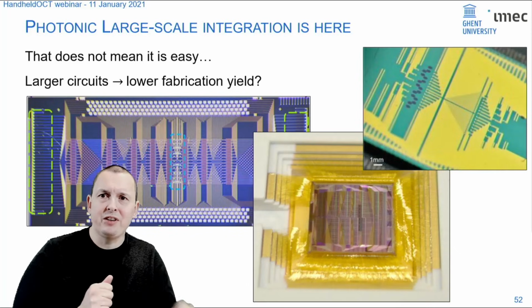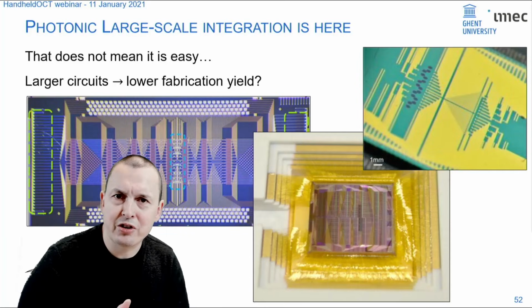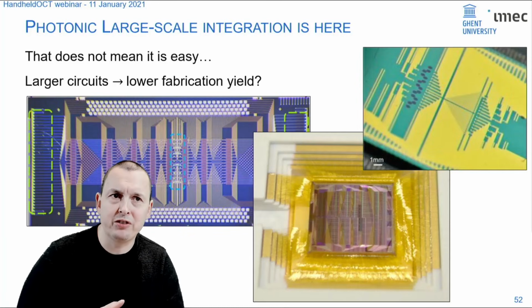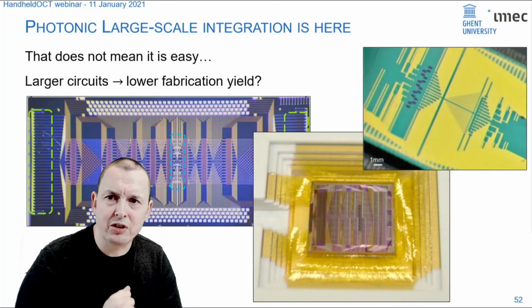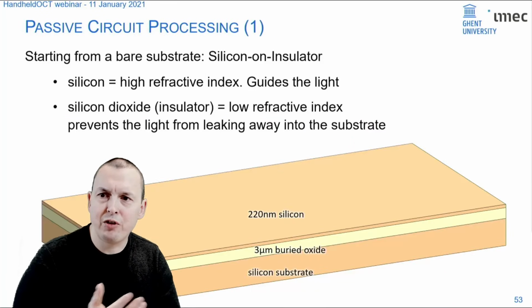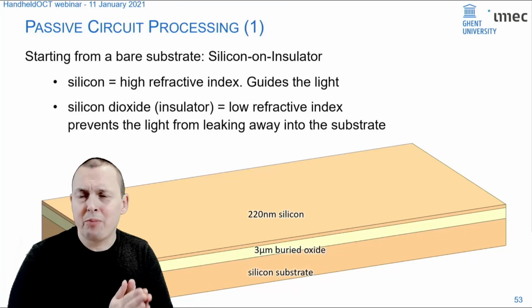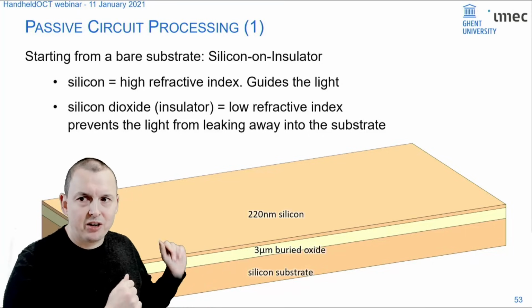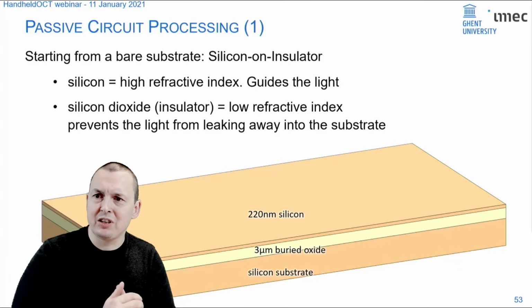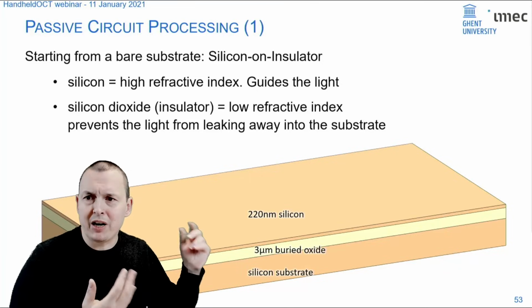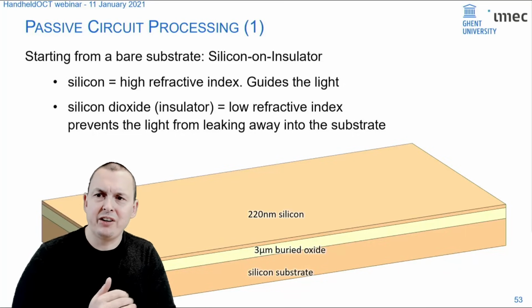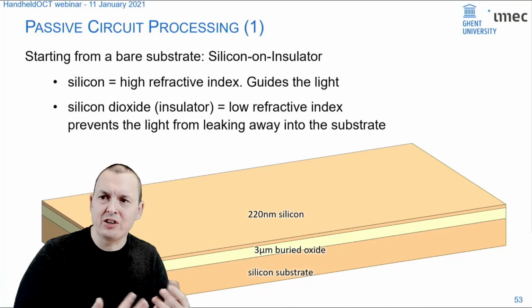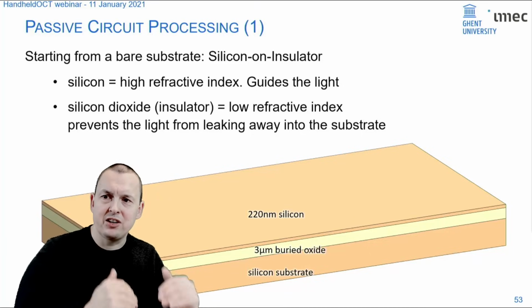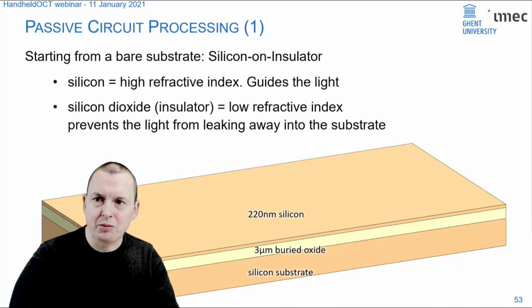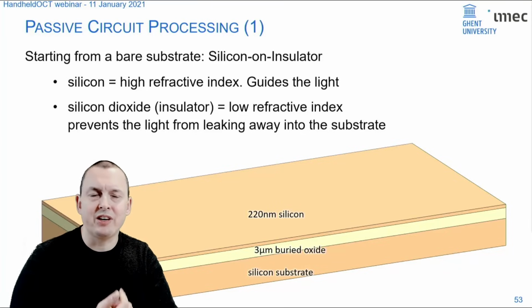Now let's dive a little bit, as an introduction, into how these circuits are fabricated, what is needed to make photonic circuits, and let's focus first on how to make the waveguides themselves. Silicon photonics is usually based on a layer stack that looks a bit like this. You have a silicon substrate, which is the wafer, and then you have 2 or 3 microns of insulator layer. It doesn't act as an electrical insulation layer. It acts as a low index layer that separates the silicon substrate from the guiding layer in silicon at the top, which is on the order of 220 nanometers.